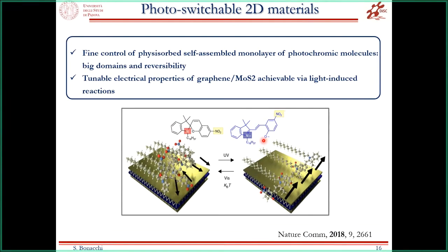like MoS2. And we, in the Paolo Samorì group, are still working on this kind of topic by playing with different kinds of tunable material and different kinds of tunable photoswitchable molecules. So this for sure opened the way to the possibility, also for chemist people like me, to play with this 2D material and to induce strange effects on this material just by playing with light and photoswitchable molecules, just by selecting photoswitchable dyes able to induce a strong and ordered dipole effect on the 2D material.